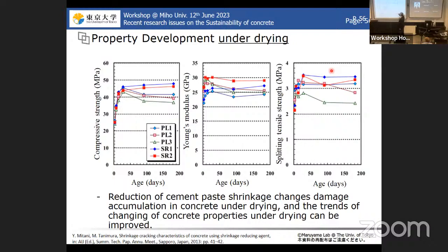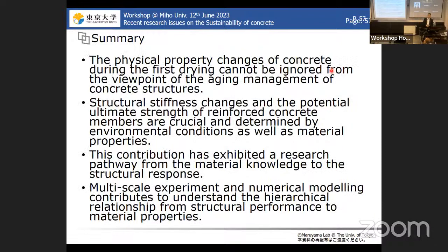And also, for the Young modulus, we see a reduction when we expose it to the drying condition. But if we add SRA, the reduction of Young modulus is very little. So therefore, not only the shrinkage induced cracking, but also the concrete property was modified. So a reduction of the damage inside of concrete could be very helpful, especially for keeping the stiffness of the concrete. Therefore, I believe that for long-term use of buildings, SRA is quite useful. This is a summary. Thank you for your attention.